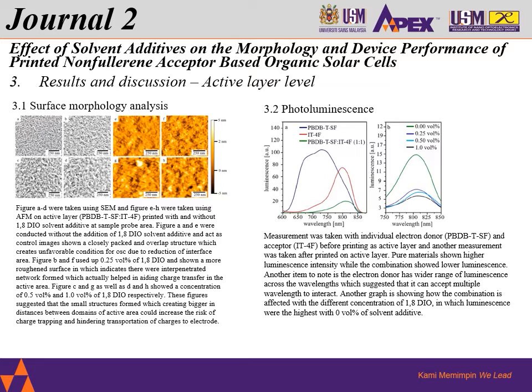But then when we increase the amount of DIO concentration, you can see that the structure is creating more and more gaps. These figures suggest that the small structures formed are creating bigger distances, so bigger gaps, and this could increase the risk of charge trapping and hinder transportation of charges to electrodes. So this is basically unfavorable.